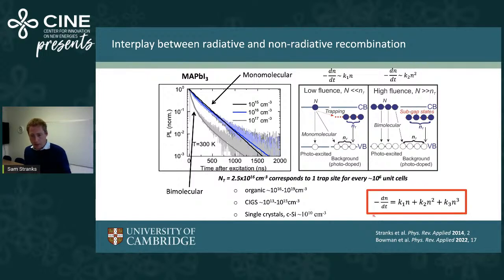But what that means is, we can think about the overall kinetic of recombination of these materials, where n is the carrier density. So we have a first order term, which dominates at low fluence and effectively relates to the trapping component. We then have this bimolecular recombination, which happens once we've saturated those traps. And if we've got a very high carrier density, we start to see third order Auger type processes, which I'm not going to talk so much about today.